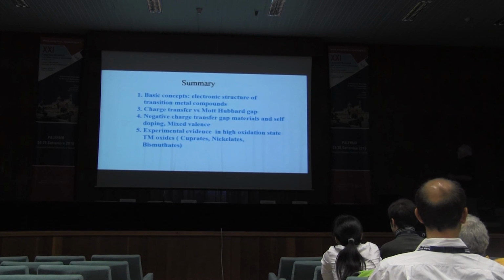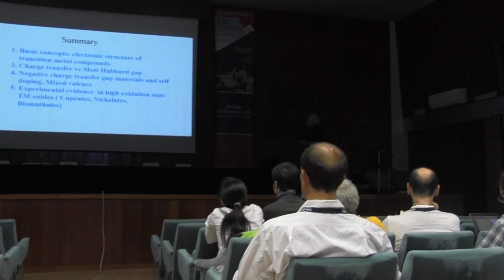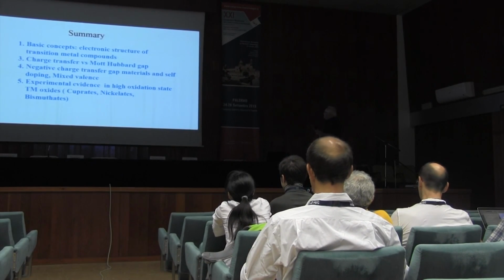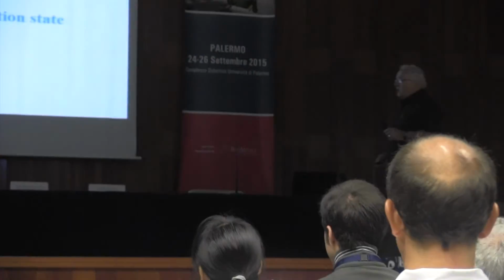Okay, so in summary, I'll talk about the basic concepts of electronic structure of transition metal compounds. I'll talk about this charge transfer versus Hubbard, but then I'll go to these so-called negative charge transfer gap materials, and self-doping, and mixed valence. And these are systems where you have a different starting point than we generally do. And that's a starting point where you can't really start with simple little clusters. Experimental evidence in high oxidation state transition metal compounds that you have this negative charge transfer gap, I will present with the doped cuprates, the pure nickelates, and also the bismuthates, which also are perovskite structure, and are superconductors if you dope them with potassium or with lead.